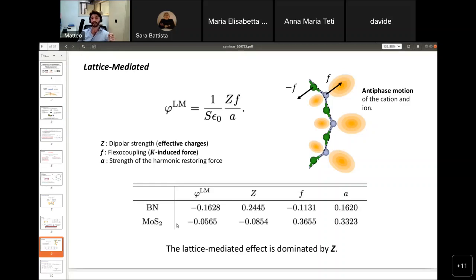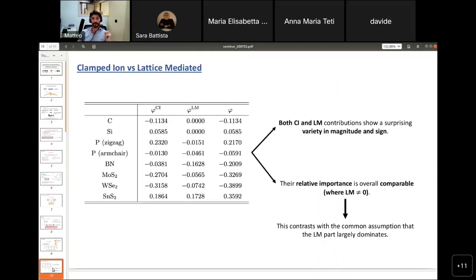Now, we have taken a look at the Clamped Ion response, and then at the lattice-mediated response. But what about the comparison between the two effects? If we look at the comparison, we find that both the Clamped Ion and lattice-mediated effects, first of all, show a surprising variety in magnitude and sign. And in addition, their magnitude is overall comparable. This contrasts with the common assumption in bulk materials and in perovskites that the lattice-mediated part dominates.